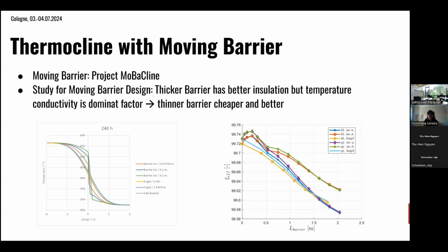The outcome basically was that it's not the heat conductivity, it's the temperature conductivity that is the most important factor here. The temperature conductivity also contains the density of the material, so actually the ability to store heat of the barrier itself. That's why we actually ended up with a thinner barrier. And if you also think of it from a practical reason, thinner barriers are much easier to design.